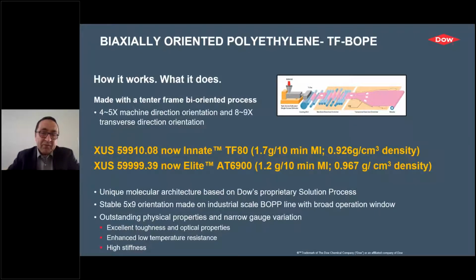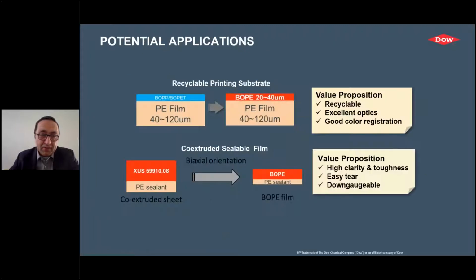One is an LLDPE with 1.7 MFI and a density of 0.926. The other one is an HDPE with a density of 0.967. And this polymer provides films with excellent toughness and optical properties, very good stiffness, and low temperature resistance, so you have a very tough material.